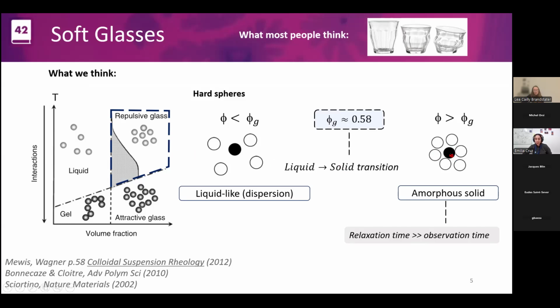And this happens because simply each colloid is surrounded by neighbor particles. So now the dynamics of that colloid that was freely moving in the liquid are frozen. And then it's an amorphous solid because there's no really an induced structure in this case. It's just frozen dynamics that occur by the caging of the colloidal particles, and it behaves like a solid, because even if I look for a long time, the relaxation time will be longer. So nothing really moves. We have made a soft glass, so a solid that's amorphous, and there's no chemical bonds. It's just happening because of that filling, spanning space with colloidal particles.